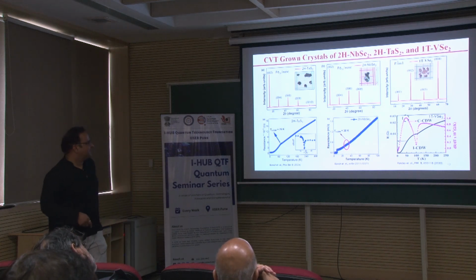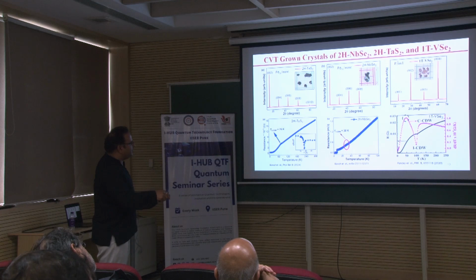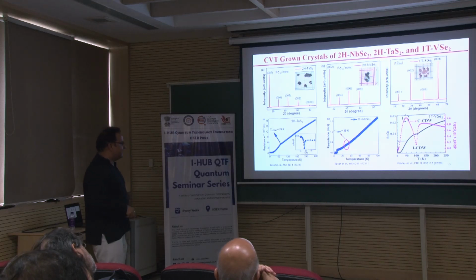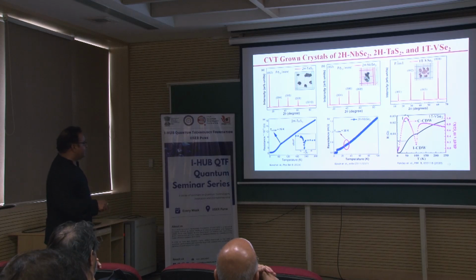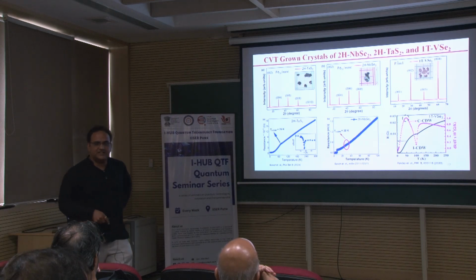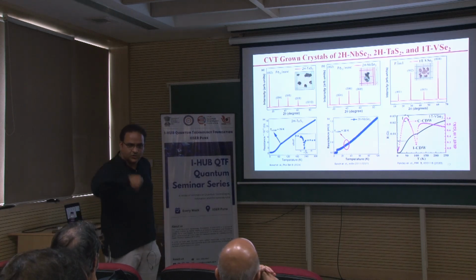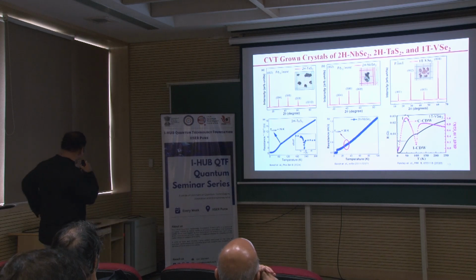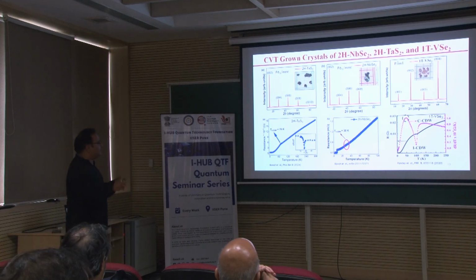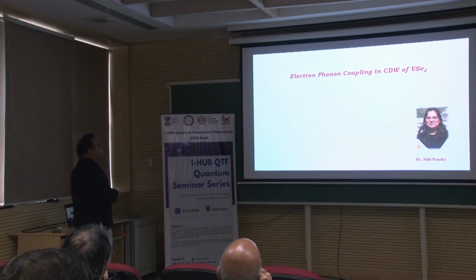7 Kelvin, sorry. And you have VSe2, which shows both kinds of charge density wave, the incommensurate and the commensurate charge density wave, which is visible here in the transport data, and this is the differential resistance here. Now, you see it has a higher temperature because there is a competition between superconductivity and charge density wave, that is why the charge density wave transition is lower for the niobium selenide. Alright, these all are bulk.